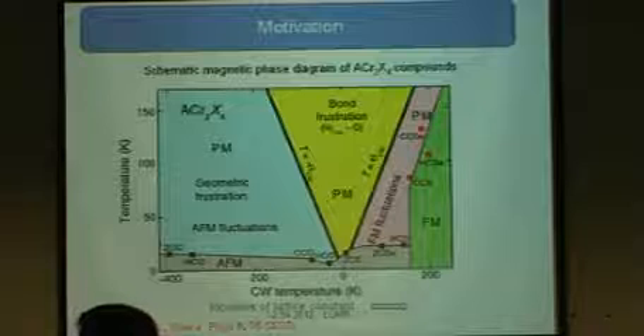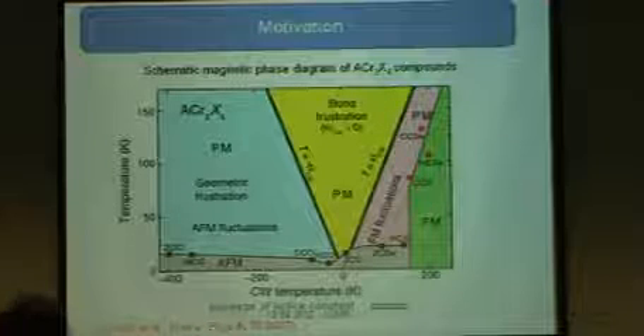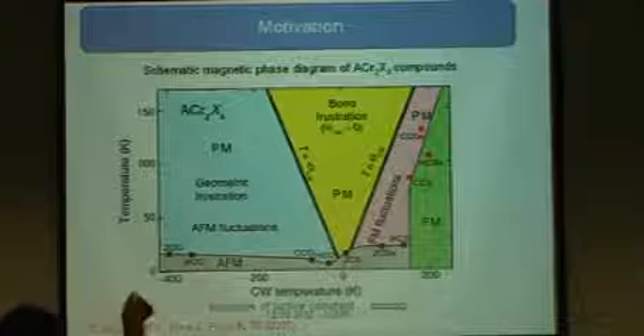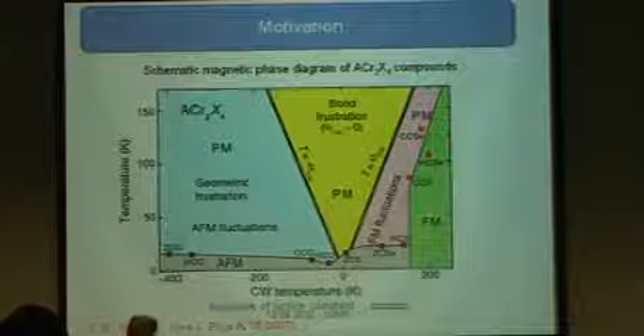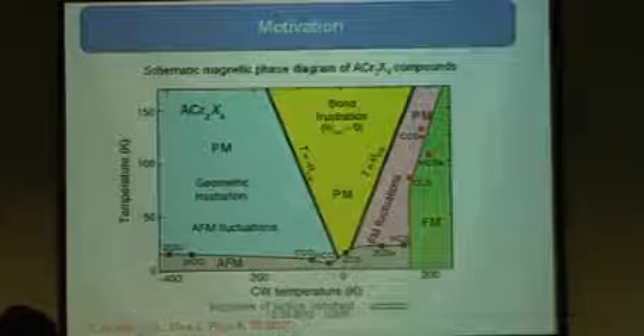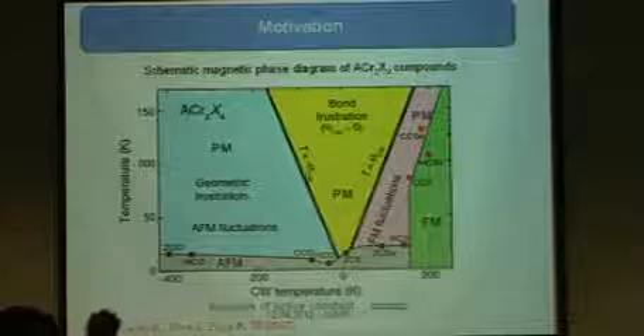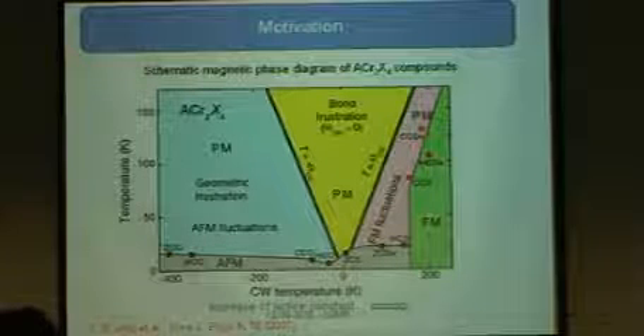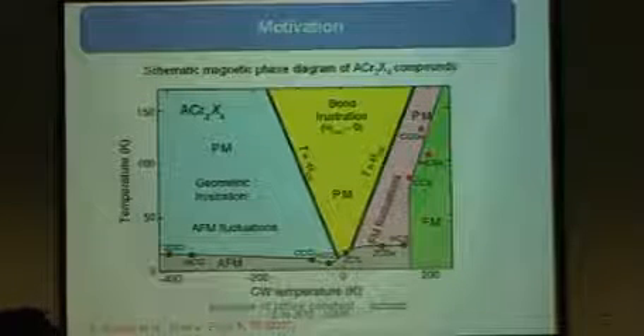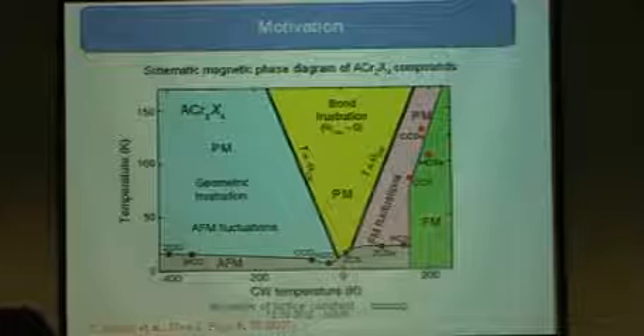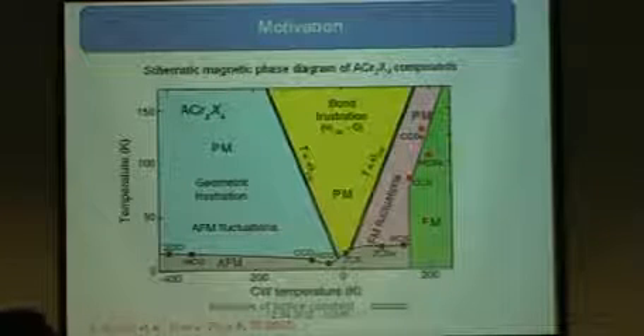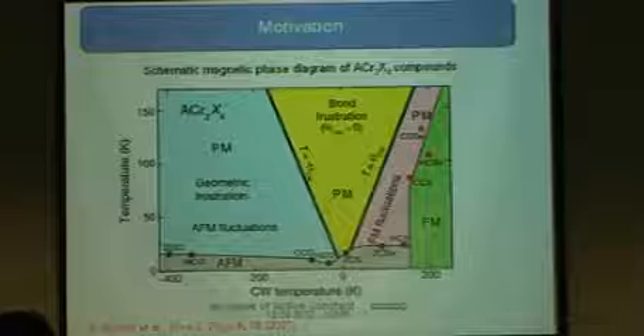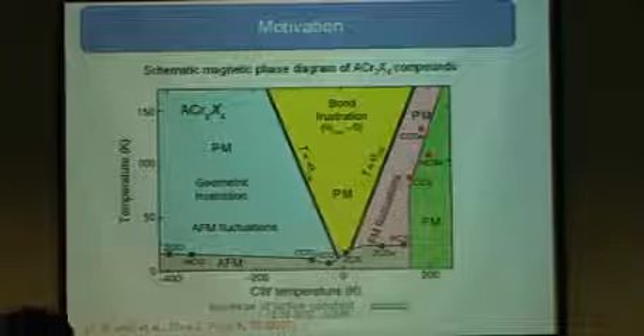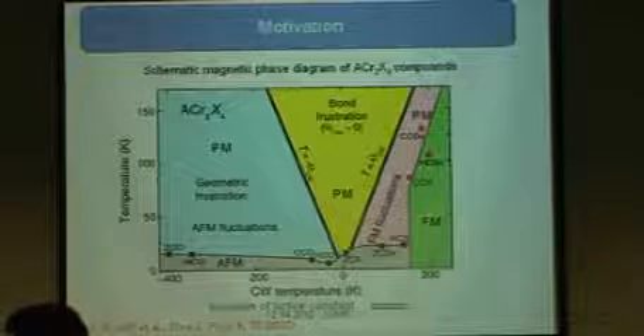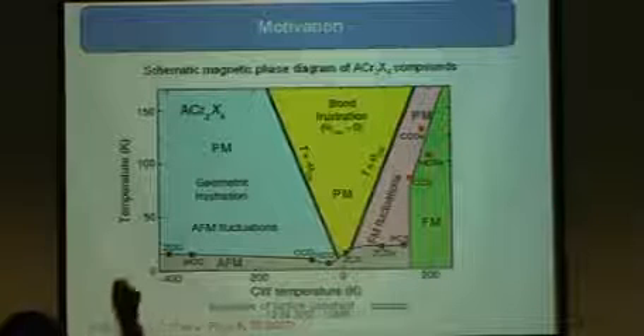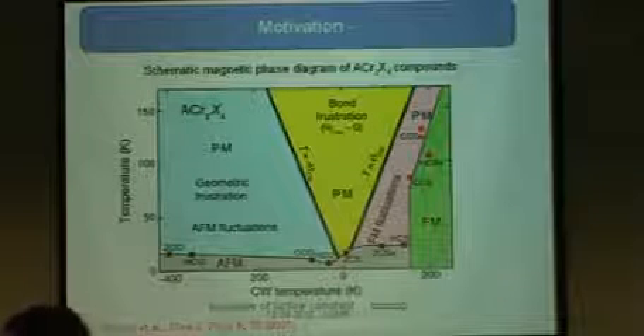What I can see is the red dots for different materials. That is the particular Curie-Weiss temperature of that material, and it is measured by measuring the magnetic susceptibility versus temperature and extrapolating the curve back to the axis, where you say the long-range order will disappear and give way to paramagnetism. So for every sample there is a point, these red or black dots.